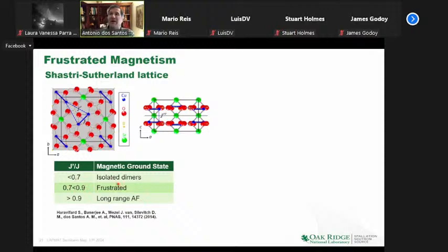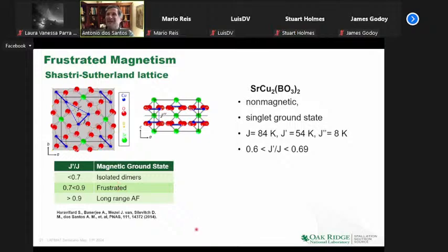frustrated. And we were lucky because chemists came up with this strontium copper borate, which is tetragonal in ambient conditions. It is not magnetic and has a singlet ground state, and it's pretty much a prototypical Shastry-Sutherland-like realization in nature. And so it was really interesting to know what would happen as you change pressure. How are we playing with this J over J prime?